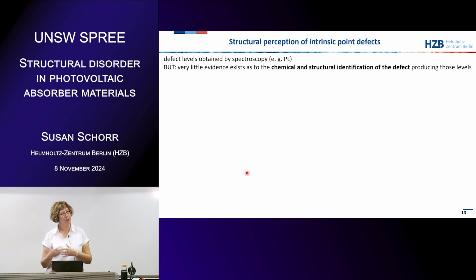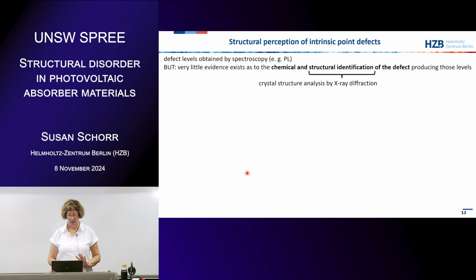Then normally you measure these defect levels by photoluminescence. That's fine, but from the PL measurements you only know where these levels are in the band gap, but you don't know the defect producing that level. So from PL you only get the energy level, but not the chemical and structural identification of the defect producing that level. So we do this by X-ray diffraction. We do the structural identification of the defect.